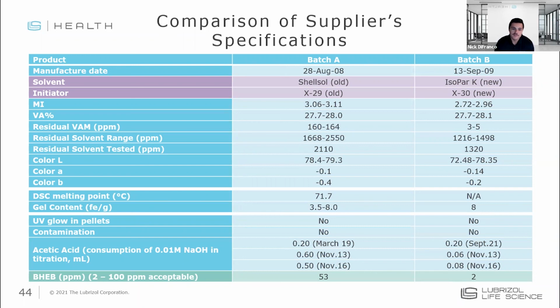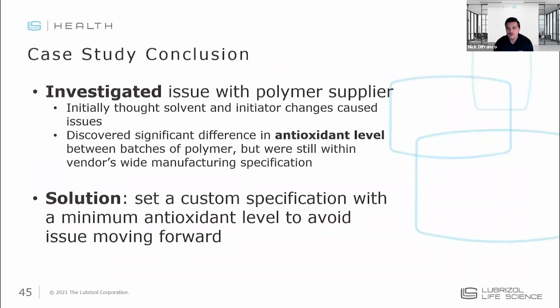In the past, we had received material that was right in the middle of that specification. The batch that we had received, where we were exhibiting yellowing, happened to be on the low end. So we did some further work investigating this issue, and eventually ended up settling on this as the cause of the challenges we were facing, and actually setting a minimum antioxidant level in the polymer to ensure that we could get consistent drug product on the other end.